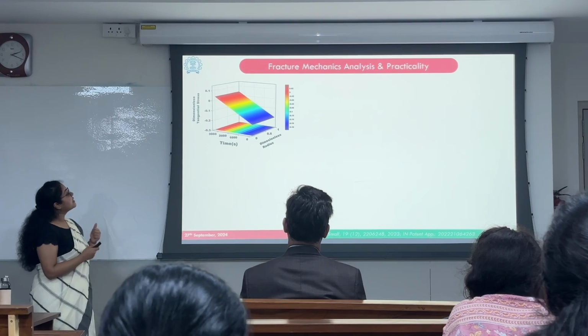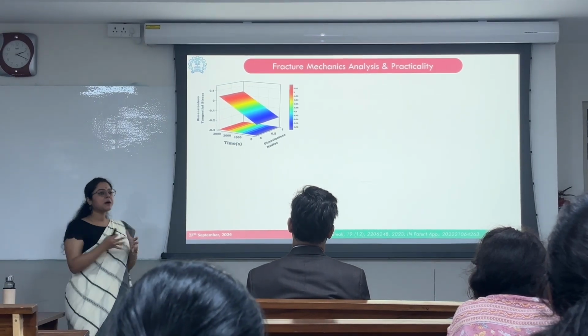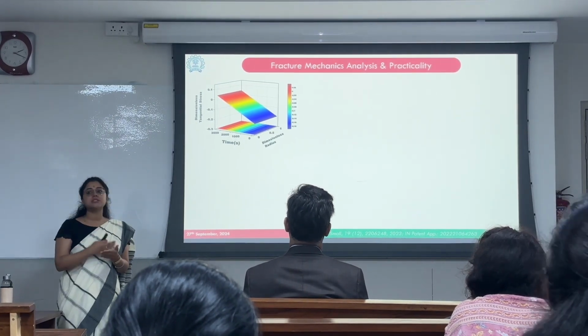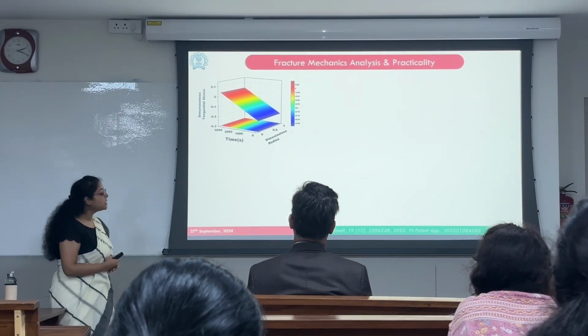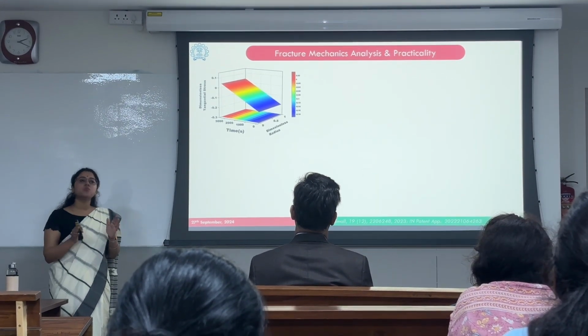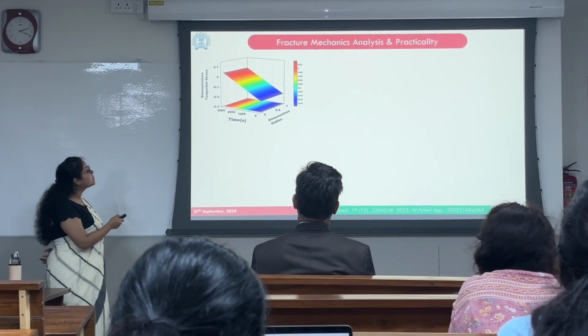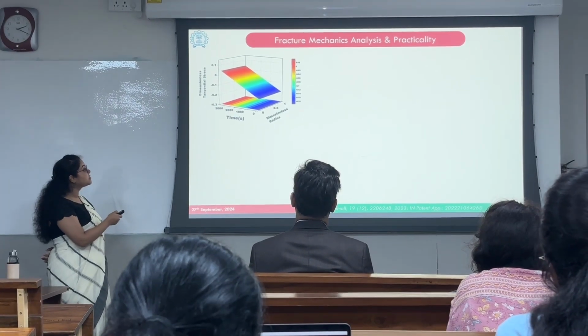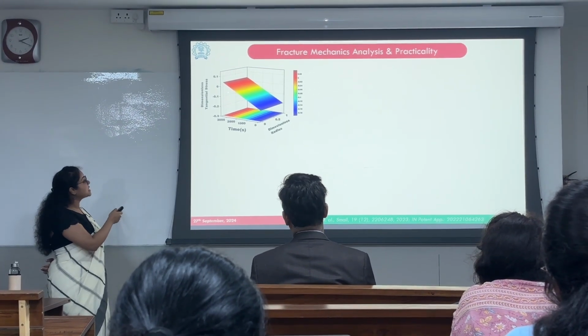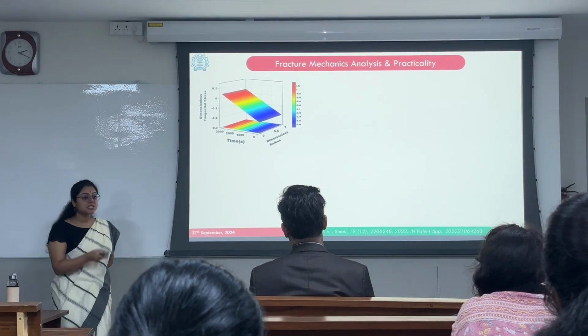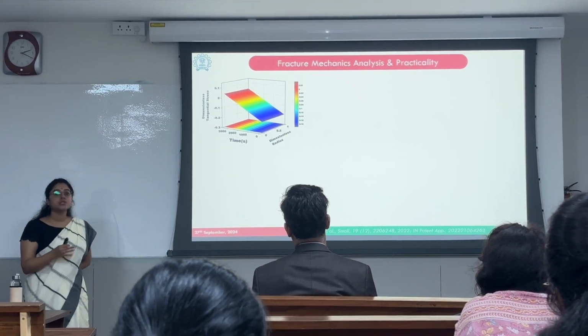To quantify this hypothesis, we conducted the fracture mechanics analysis with the help of Mr. Jeet Ghosh, and we considered particles ranging from 25 nanometer to 25,000 nanometer, and we charged them at a C rate of 1 C. And we saw that with increase in dimensionless radius and increase in time, the tangential stress kept on increasing, which suggests that the particle size has a crucial role to play.